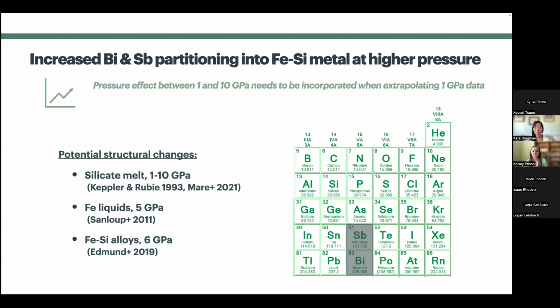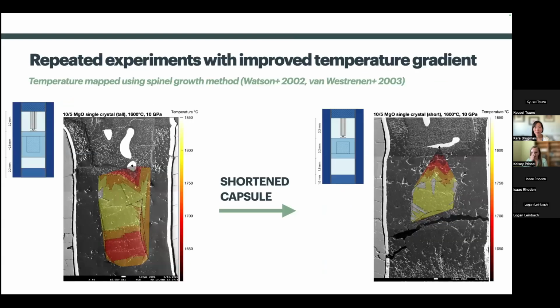The other thing, thinking about temperature, that I'm going to talk about a little bit is the temperature gradient in the sample. One of the things that I did for this project is we were originally starting out with pretty large capsules because we're using these pre-machined single crystal MgO capsules, and they were slightly taller than the usual 10-5 assembly. So I used the spinel growth method of looking at the temperature across the assembly, and was able to map out the temperature for our capsule and see that half of our capsule was significantly colder than the other half.